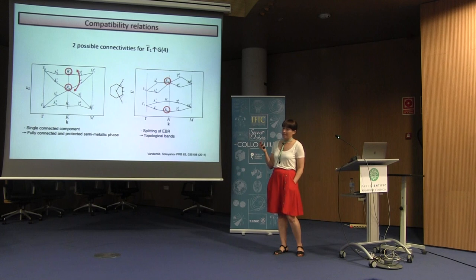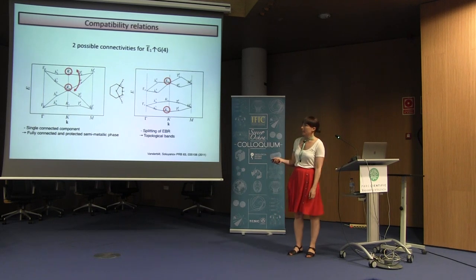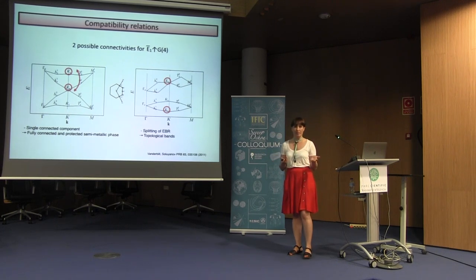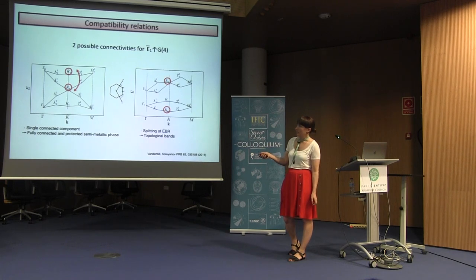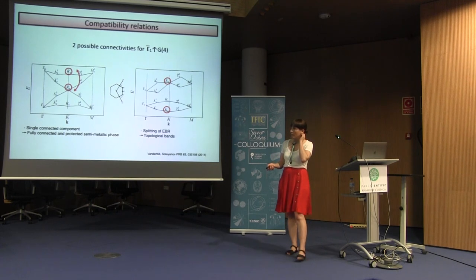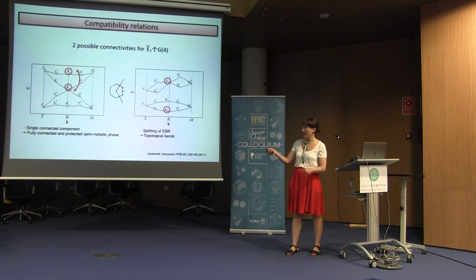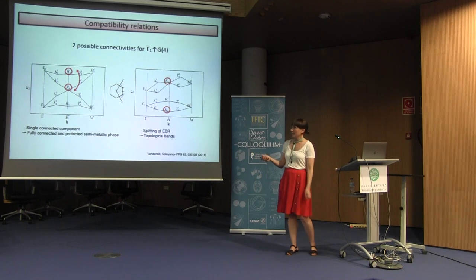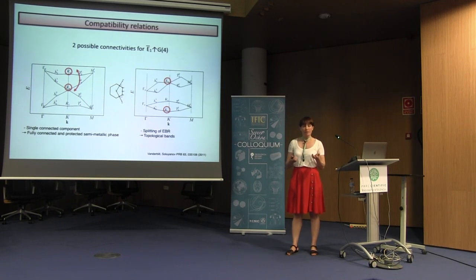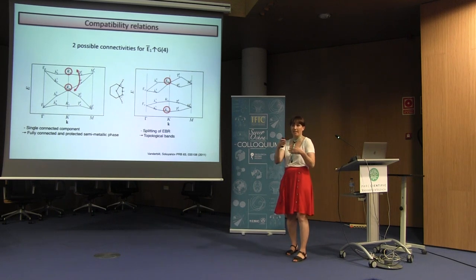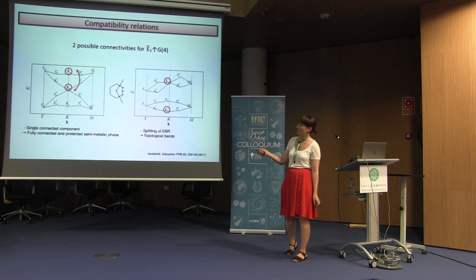But there is another ingredient we need to take into account. So, I have the information of what happens at high symmetry points. How can I study the connectivity of the bands? Because, for example, in this case, which is the induction of a PX, PY orbital in a honeycomb lattice, we have this famous Dirac cone, right? But I have no information about the energies. So, the fact that I have a Dirac cone is related to the fact that I decided to put this order of the little groups in the K point.